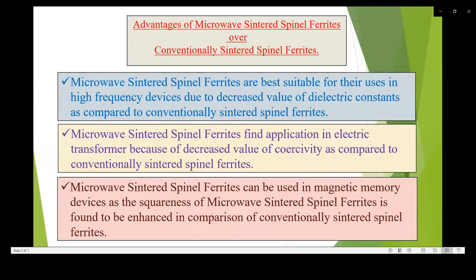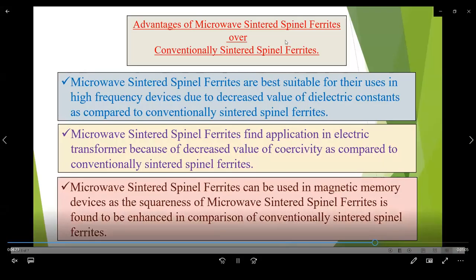Microwave sintered spinel ferrites find application in electric transformers because of the decreased coercivity as compared to conventionally sintered spinel ferrites. Microwave sintered spinel ferrites can be used in magnetic memory devices, as the squareness of microwave sintered spinel ferrites is found to be enhanced in comparison to conventionally sintered spinel ferrites.